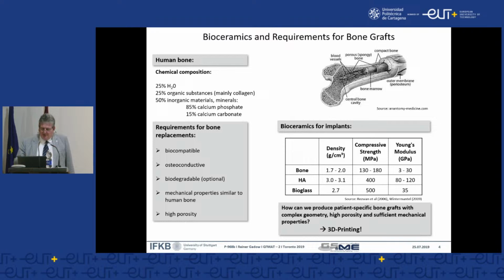And I remember also as a young researcher, if you think of such a sensitive mechanical structure, why should I integrate glass? We know glass has a sensitivity to fracture, so we don't like to work with this material, no? The reason is, this is not a silicate glass as we know it from packaging and so on. This is a glass that has a chemical composition which perfectly stimulates the metabolism to have natural bone cells growing on its surface. That is the main background.